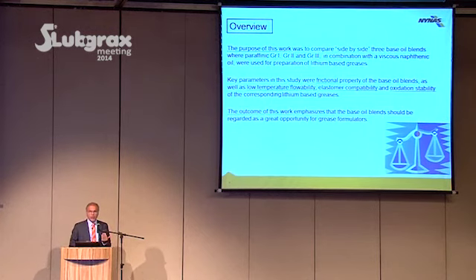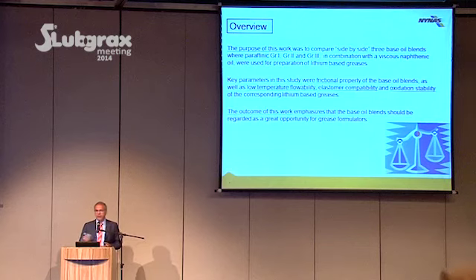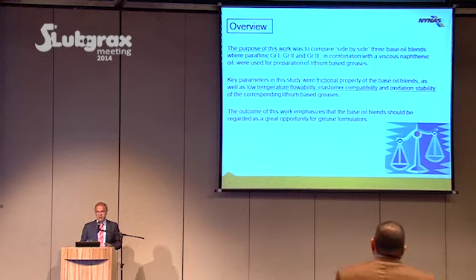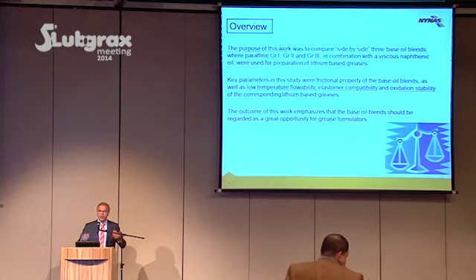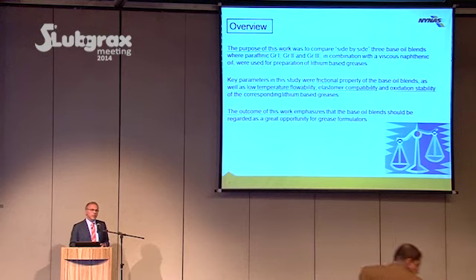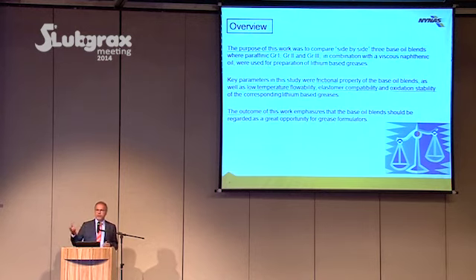So, and then we characterize the product, the blend, with some typical characterization as we do regarding the base oils, but also some unusual ones, like frictional behavior, elastomer compatibility, and so on. And when it comes to greases, we also studied the low temperature flowability and elastomer compatibility. Elastomer compatibility is very crucial to, for instance, the automobile industry.